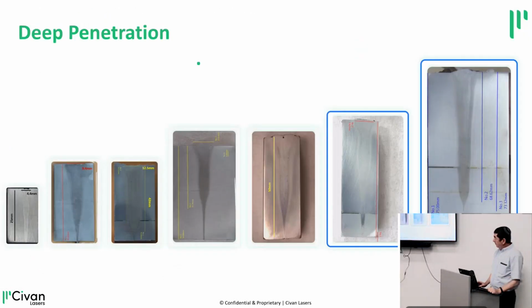So these are some examples that we did. The first few are 25 millimeters, 40 millimeters, 50 millimeters. Up to here, we can do with a 16 kilowatt laser. This we do with a 32 kilowatt laser. And this we did with a 100 kilowatt laser. This is already 3-inch. I have the sample here. Afterwards, I'll show you. So this is really very, very special.